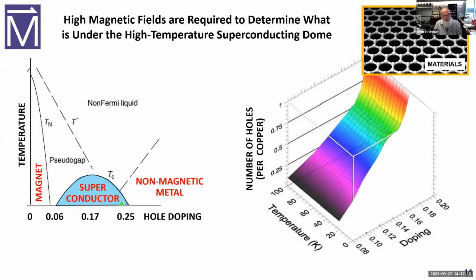So it was exciting initially that these things superconduct up to 100 Kelvin, but now that's an annoyance. I want to peel back this superconductivity to see what's happening underneath, what's giving rise to the superconductivity. So over here, we've plotted in low magnetic fields, what are the number of mobile holes per copper as you increase this hole doping? And as you might expect, as you increase the number of holes, in other words, remove more and more electrons as you move this way, then you're getting more and more mobile holes, mobile charge carriers. But you can't tell what's happening at low temperatures because the darn superconducting phase gets in the way.